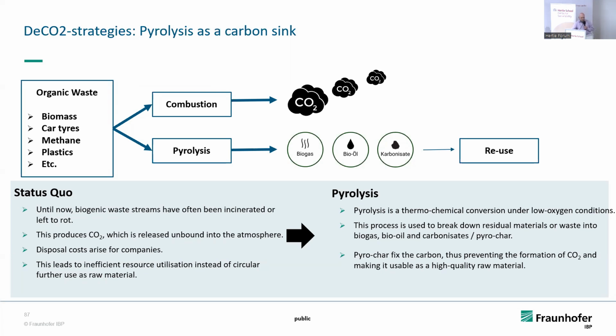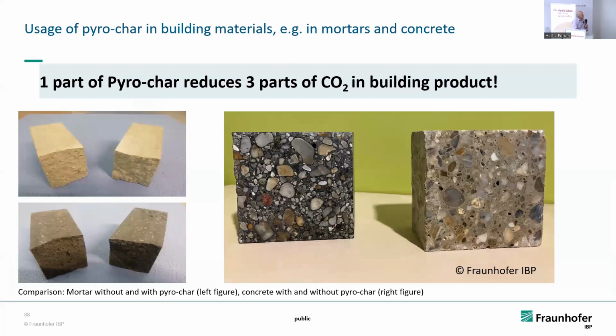And now the big idea is to use this pyrochar, these carbonizates, in building materials, which you see here. Here were our first trials with mortar, and on the right-hand side, we used concrete and added pyrochar to the concrete. Take these numbers: 1 part of pyrochar reduces 3 parts of CO2 in your building material. The first idea was to use this pyrochar just as an additive. And there were some challenges. You can't just throw pyrochar into concrete, it will swim at the surface. But we have some tricks. We also now have a patent to modify this pyrochar so that it can be mixed together with concrete.